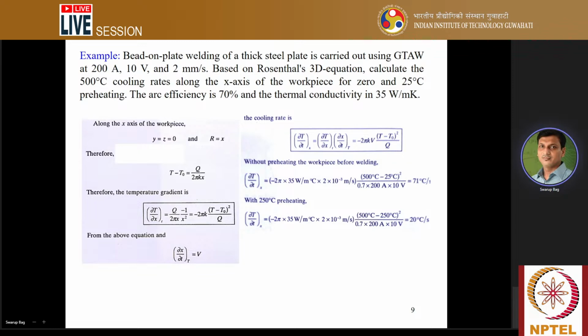Oh, sorry, it should be 250 degree centigrade preheating. It must be 0 and 250 degree centigrade preheating. The arc efficiency is 70% and the thermal conductivity is 35 watt per meter Kelvin. So these values are given. Now we try to solve this equation.